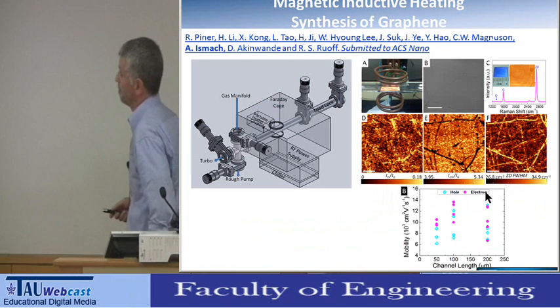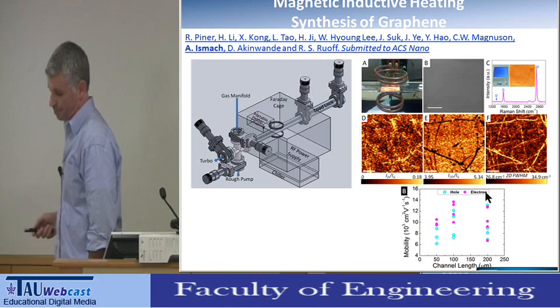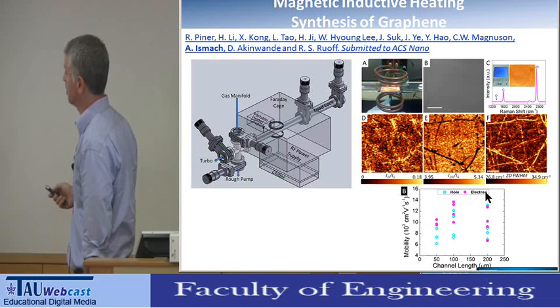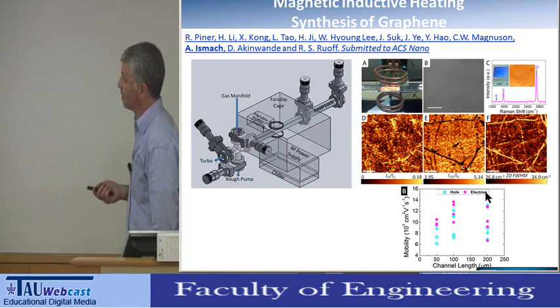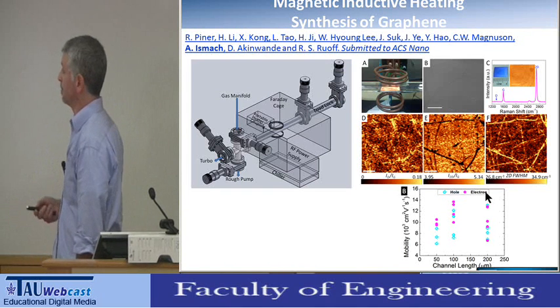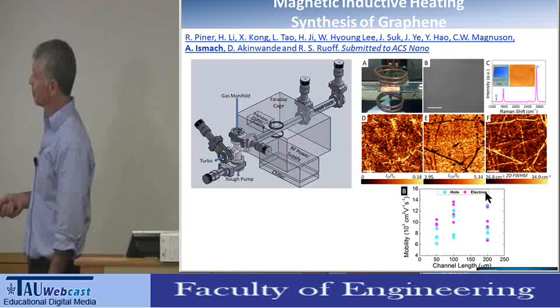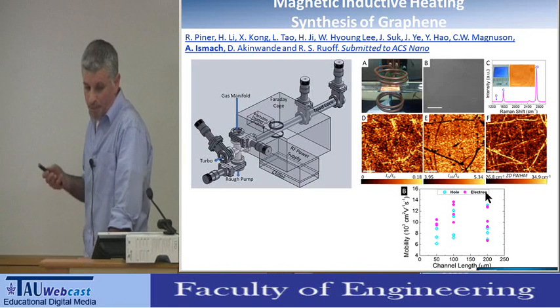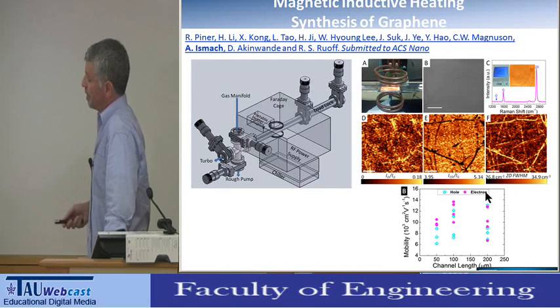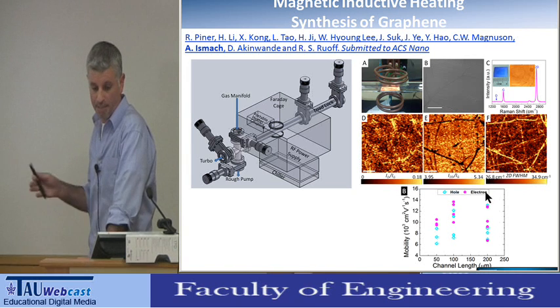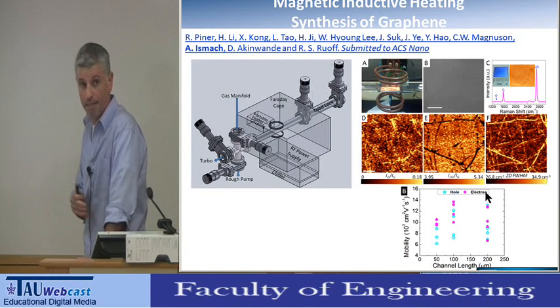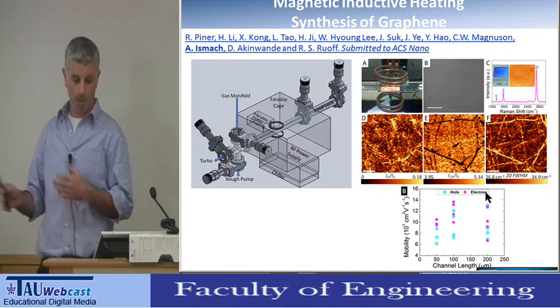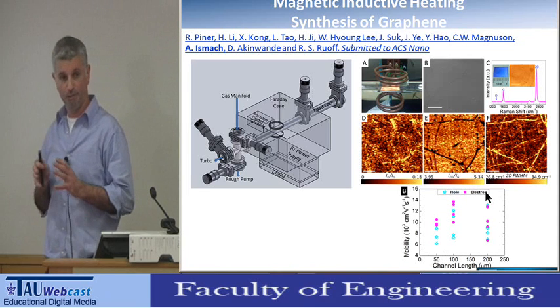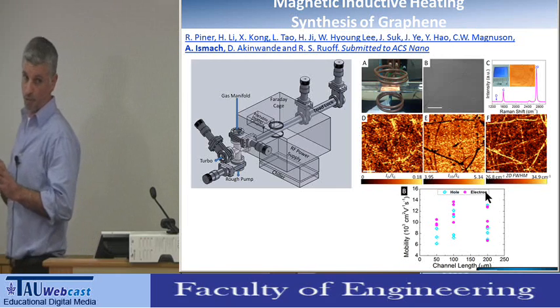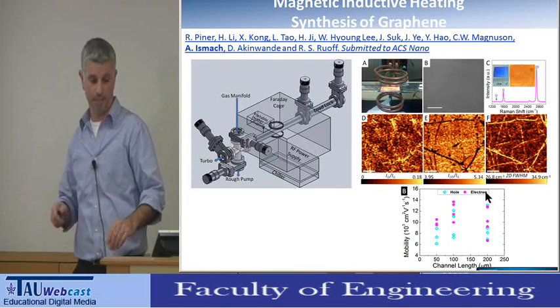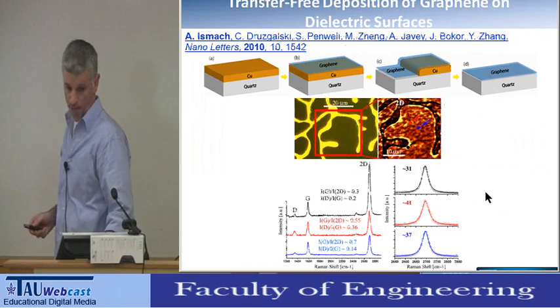Then just a few words about a different system that we just finished building and are trying to publish, in which instead of using a hot wall system, we are using magnetic inductive heating, which is a cold wall system. In principle, it's very much the same process, but by this methodology we are supposed to have more flexibility in heating the surface, and also in local heating. So we are trying to do some kind of single crystal graphene growth as it is done in 3D, like moving the stage during local heating of the copper. But this is something that we're working on now.